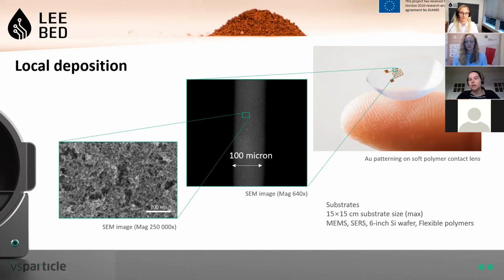For substrates, you can use, as shown here, polymers, but also any substrate that is solid in some form, like MEMS, SERS chips, a 6-inch wafer. The only condition is that it needs to fit into the vacuum chamber. So 15 by 15 centimeter is the maximum size that you can put in there. The print process does not require electrostatic deposition, so the substrate does not need to be conductive. It can be a polymer, for instance. It does, however, need to survive a 0.2 millibar vacuum. So that limits a bit how moist your substrate can be.